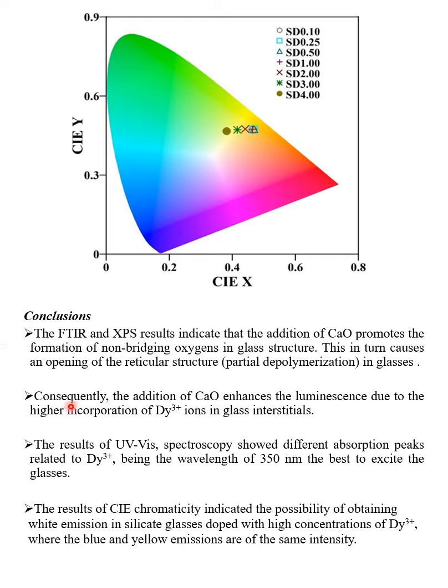formation of non-bridging oxygen in the glass structure. Consequently, the addition of calcium oxide enhances the luminescence due to the higher incorporation of the dysprosium ions in the glass interstitials, and the CIE chromaticity indicates the possibility of obtaining white emission in silicate glasses doped with a high concentration of dysprosium.